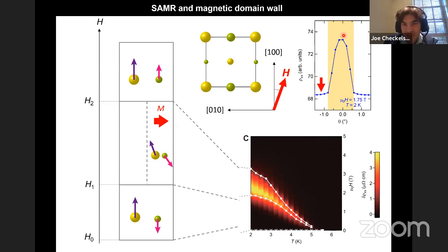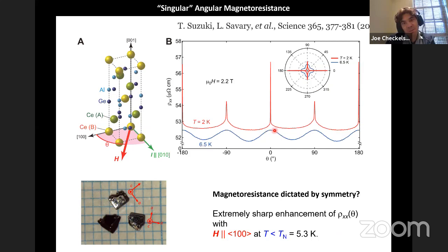So what you could probably say is that just from the tilting of the moment, you get a change that's something like this. You can sort of fit how much the moment changes as a function of field tilt angle. And really what you see is there's this additional thing on top. But you're right, just from the rotation of the moment, you would also expect this. You can also kind of see that even from this part of the phase.